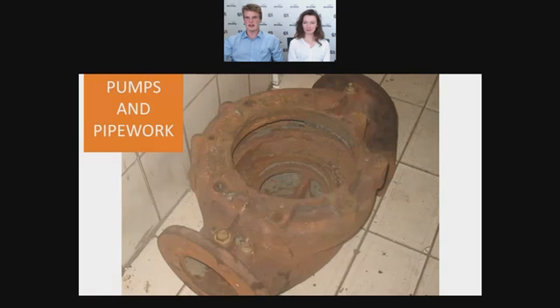To take this sewage pump here, we can see it's very heavily corroded and damaged. Most asset owners would probably discard this pump and replace it with a new one. However, it is possible to restore these pumps to bring the efficiency back up for the long term using epoxy solutions. This can be a much more cost-effective solution. In fact, based on previous experience, the cost of an epoxy solution is around 20% the cost of replacing a pump outright.